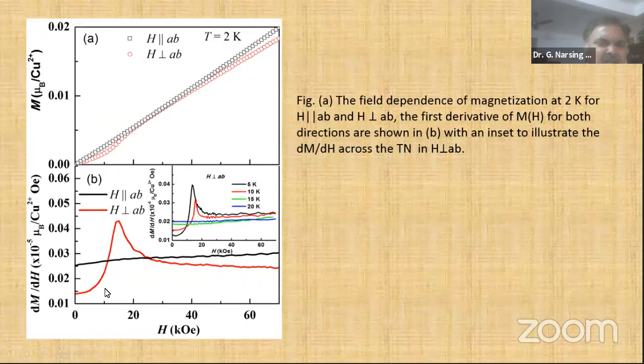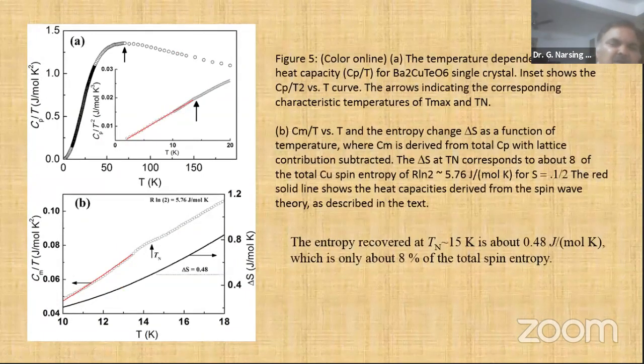But parallel to AB, there is no change in dM by dH. Here there is a change for H perpendicular to AB, which means parallel to C. Perpendicular to AB means parallel to C. And along C, a different spin structure is acting. Similarly, heat capacity should show exactly where the transition is, but here the transition is not showing anything, only a small kink at 15K.